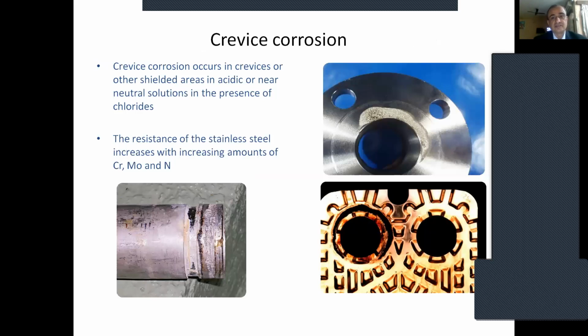Crevice corrosion is found in flanges, pipes, fittings, where there is a shielded area, in acidic or near neutral solutions in the presence of chlorides. The resistance of stainless steel increases with the increasing amount of chromium, moly, or nitrogen. Again, the same thing: when you increase the chromium, moly, or nitrogen, it increases the corrosion resistant properties as well. So this crevice corrosion also occurs.